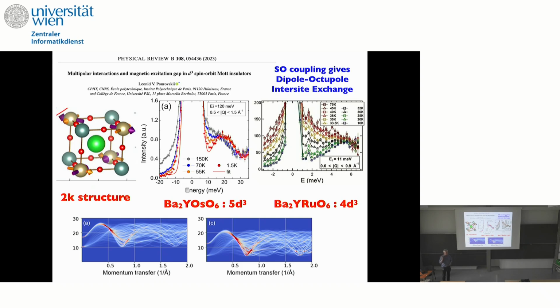And it turns out that multi-domains of a 1K antiferromagnetic structure, a 2K antiferromagnetic structure and a 3K antiferromagnetic structure all give you exactly the same sequence of Bragg peaks and intensities. So this is referred to as the phase problem in crystallography. We can't tell them apart.